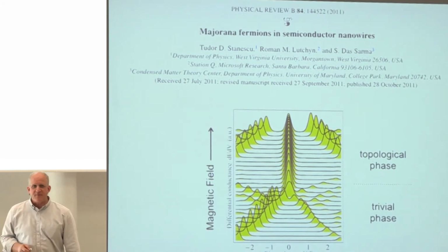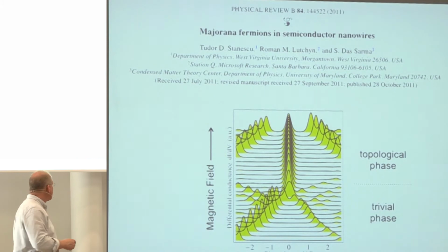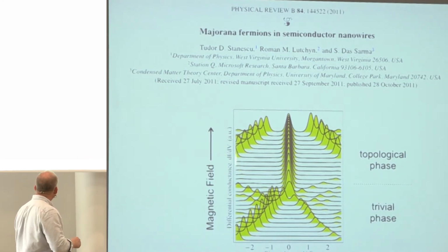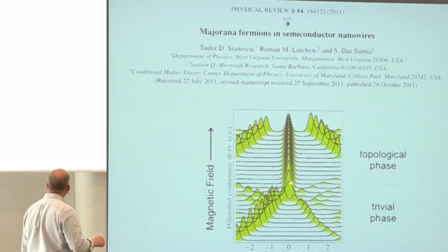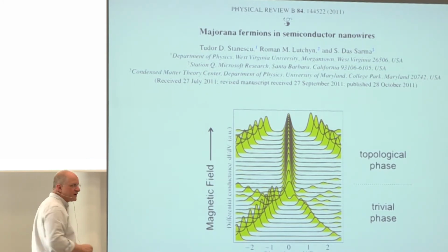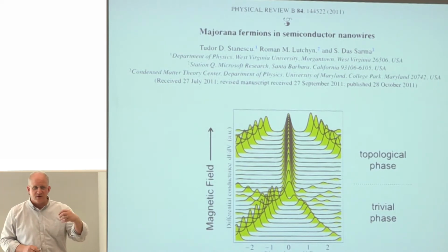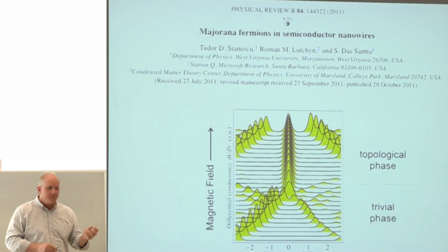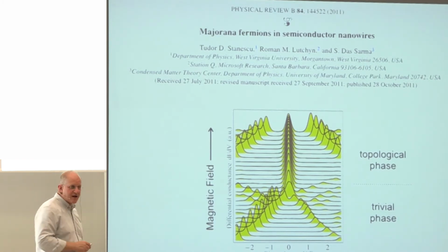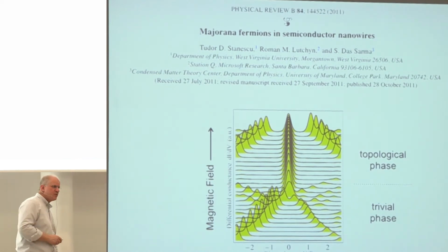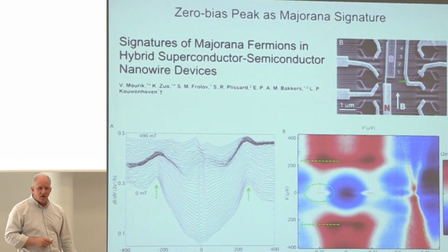So you can imagine, as you turn up the magnetic field and go from the regime which is topologically trivial, the regime in which there's a BCS density of states, and now they're calculating conductance from a tunneling experiment into a superconductor. Here's the BCS density of states for a realistic sample with disorder. As you turn up the magnetic field, those two states move toward each other, and instead of continuing to pass through each other as they Zeeman split, they form a new state, a state that lives only at zero energy and persists up to higher magnetic fields, and is the signature of the appearance of the red ball, or the topological state at the end of the wire, which would only appear as the magnetic field is raised above a certain critical value.